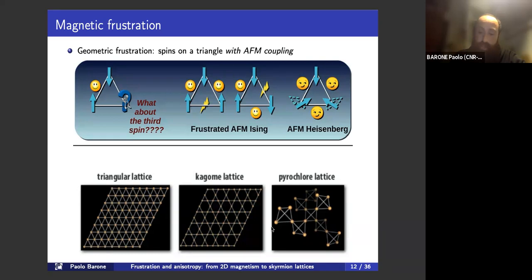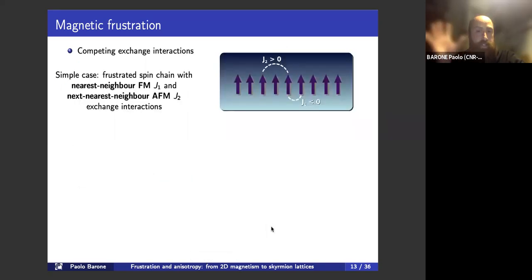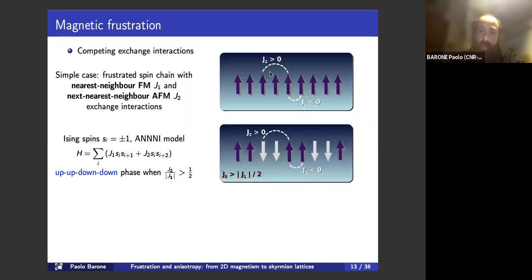One can also have frustration emerging just from competing exchange interactions in a system, in a lattice which is not frustrated. So the simplest example is just a spin chain with competing ferromagnetic and antiferromagnetic interactions. And of course, here we would have pairs that are happy because of the ferromagnetic coupling, but then the second nearest neighbor spins would not be happy because they need to pay some antiferromagnetic energy here.